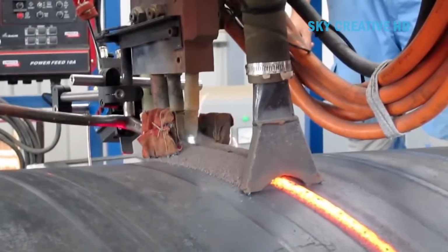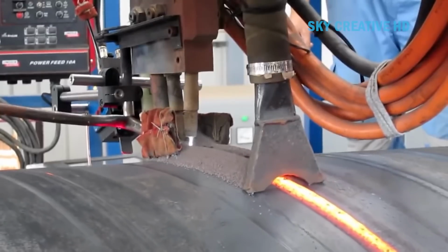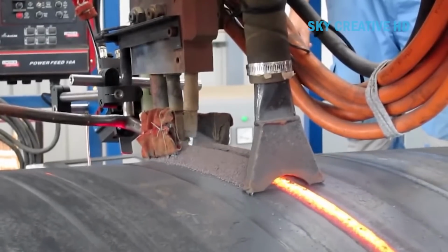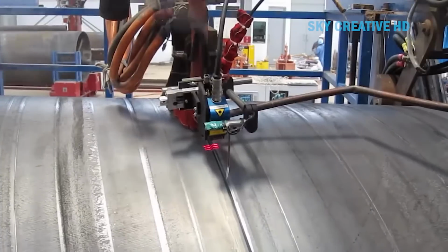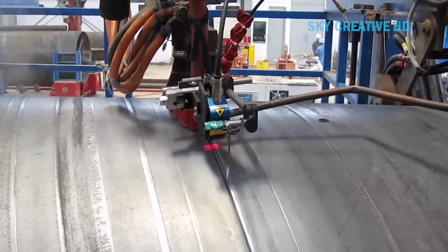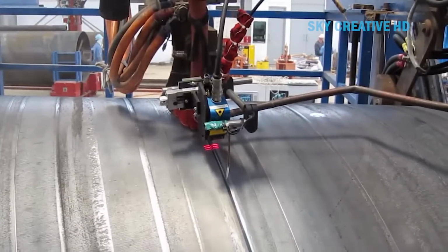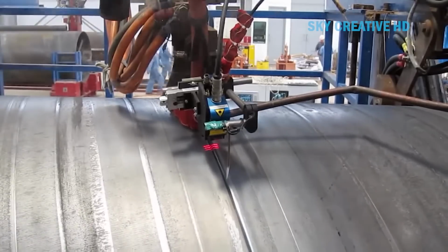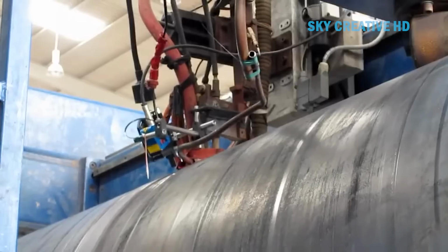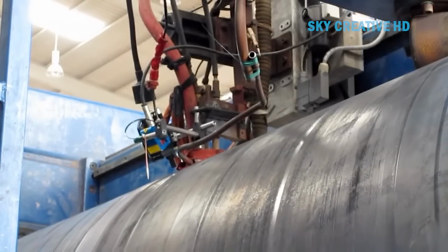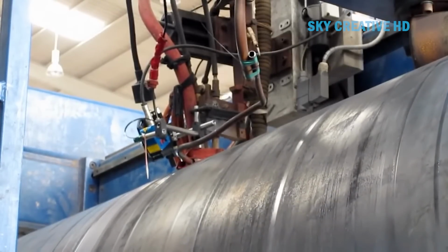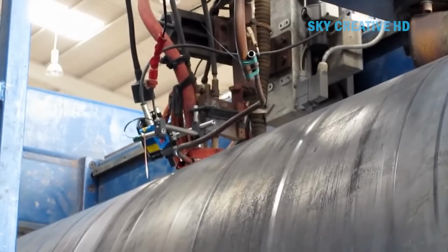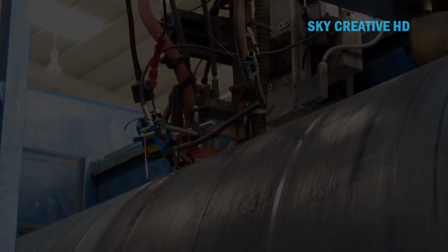High-frequency induction welding (HFIW) is a specialized option for thin-walled pipes, using high-frequency current to create a forge weld. Regardless of the method, a sophisticated welding parameters control system monitors and adjusts current, voltage, travel speed, and other factors. Weld tracking systems, often using optical or laser sensors, are highly recommended to maintain consistent weld quality.